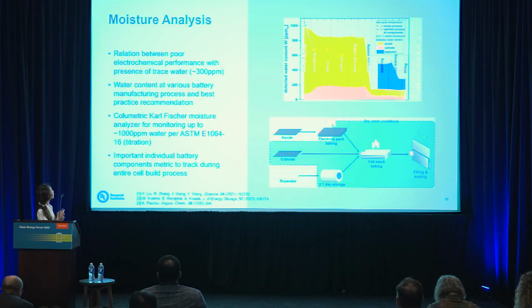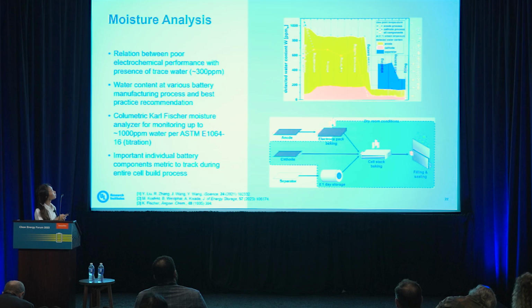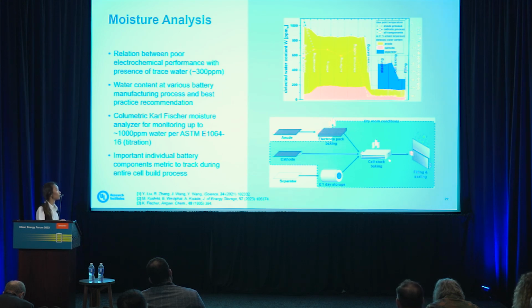This study over here looked at the water content at various battery manufacturing processes, and they had some recommendations on best practices. You can see that they measured the different anode, cathode, and separator across the different manufacturing processes. We probably all know that we do need dry rooms, especially for cell stacking as well as electrolyte filling and sealing. Of course, for anode, we are sometimes using a water-based slurry anyway, so this can be offloaded from the dry rooms. But for the majority, dry room conditions are more or less recommended.